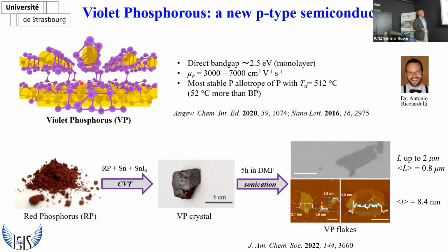And therefore, red phosphorus has been used as a source of phosphorus, and as transferring agent, tin iodine has been exploited in order to fabricate this kind of crystal, which has been exfoliated by sonication in DMF to get this kind of two-dimensional object, flakes that have a size of about 800 nanometers and a thickness of a few nanometers, namely the idea is to have 5 to 10 flakes that are piled up, stacked.